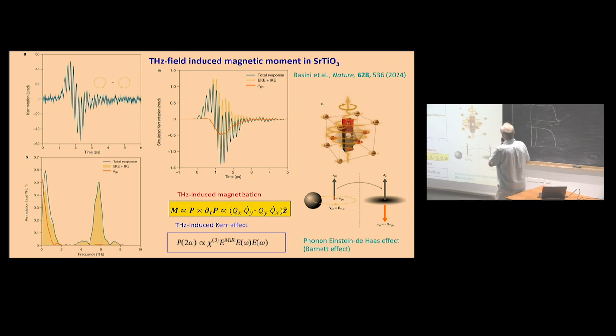The experiment was published for the first time last year by Basini. She observed Kerr rotation, meaning the magneto-optic Kerr effect in reflection. It was a single pulse measurement at room temperature, pumping with 3 terahertz. And she observed such oscillations. When she calculated the Fourier transform, she obtained 2 peaks, at 6 terahertz, which is twice the pumping frequency, and at 0.5 terahertz. Nothing at 0 frequency.